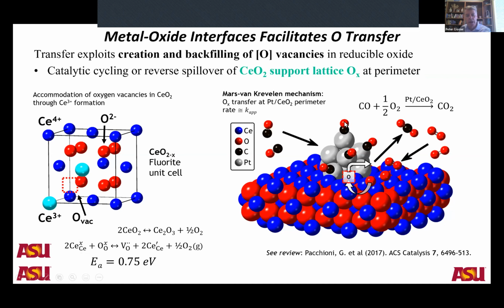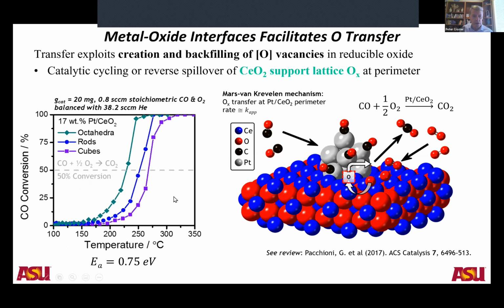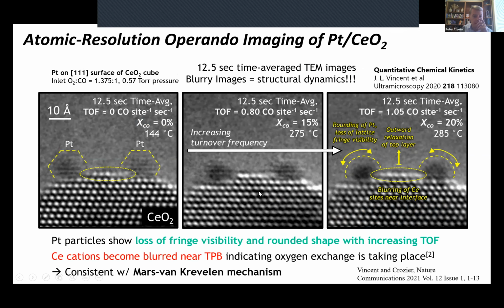In CO oxidation, the carbon monoxide chemisorbs onto the platinum with the carbon side down. The CO then migrates down to the metal ceramic interface, and the CO plucks an oxygen out of the oxide, creating an oxygen vacancy to produce a CO2 molecule. And then those oxygen vacancies are subsequently backfilled through the dissociation of molecular oxygen. So Josh was studying this. He made lots of different catalysts, and we characterized them in the reactors in the lab. And I want to just show you what he saw when he did operando experiments in the electron microscope.